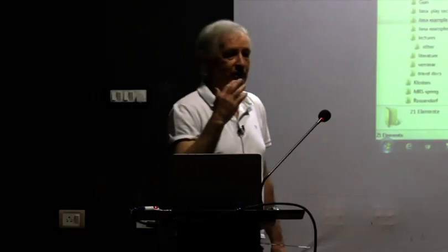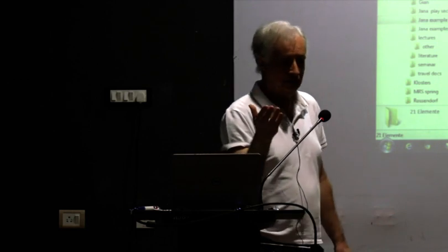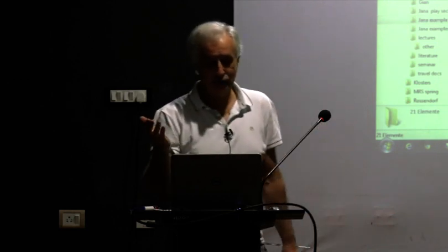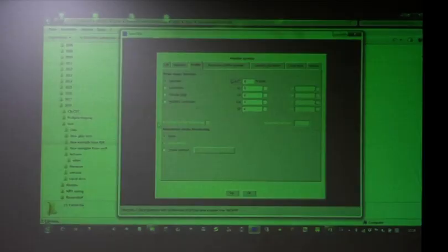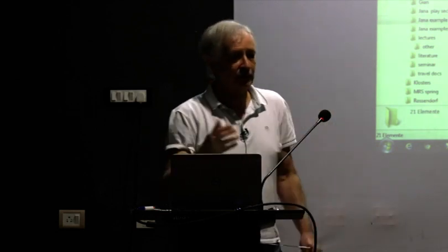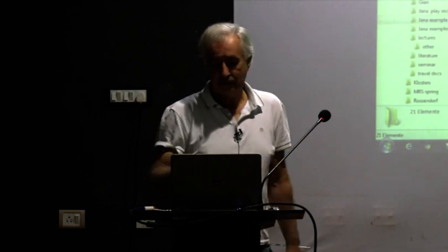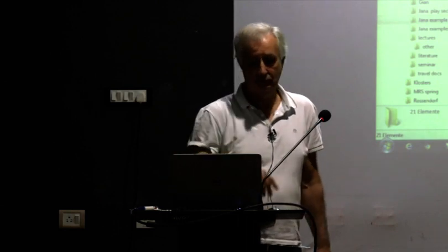When we look at profile, what is the profile? What do you think the profile of our X-rays are? Okay, they can be Gaussian, Lorentzian, pseudo-Voigt. We usually choose a pseudo-Voigt. A pseudo-Voigt is a mixture of Gaussian and the Lorentzian. Okay, usually it's a good starting point. I mean, if you're not sure. And then you have various functions here related to your Gaussian and related to your Lorentzian.